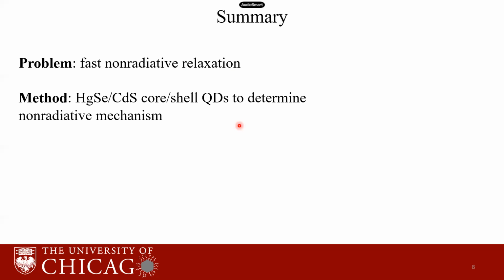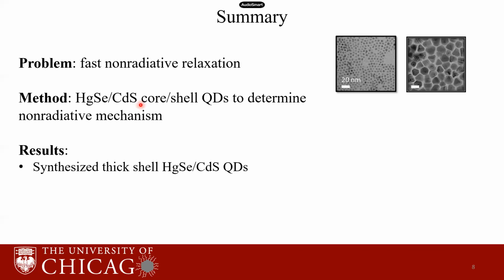So to summarize my work, the main motivation for my project is to make sensitive mid-infrared cameras which have background limited detection near room temperature. And to do this, it is necessary to slow the non-radiative decay. To find the mechanism of non-radiative relaxation, I have designed a method to grow a thick shell around the quantum dots. So we were able to grow a thick cadmium sulfide shell around mercury selenide quantum dots.